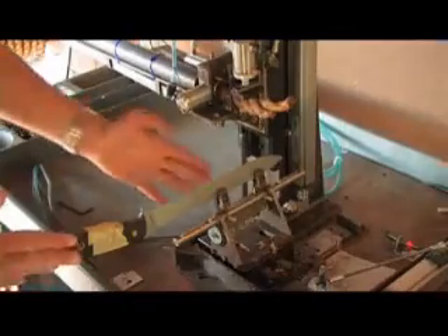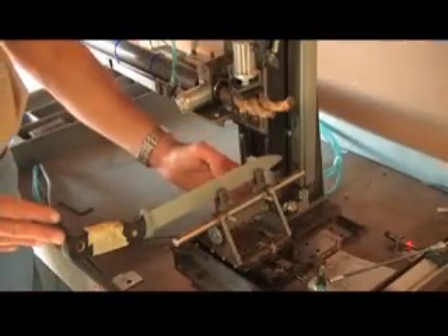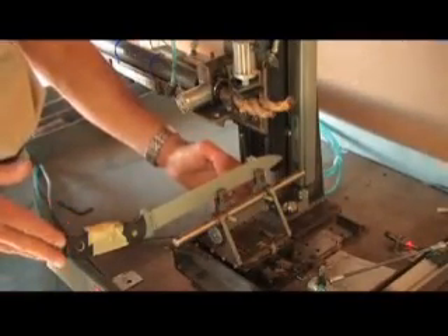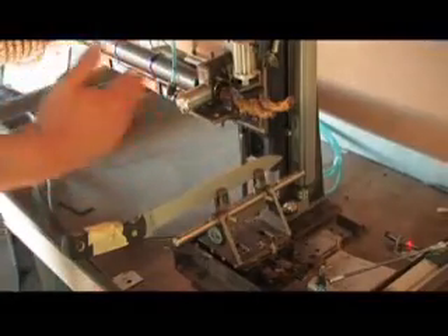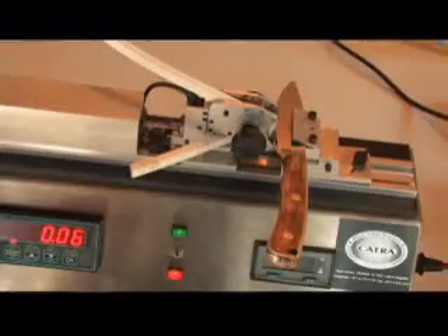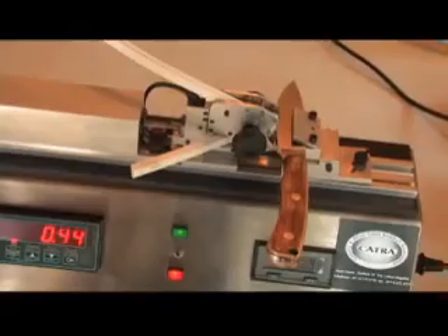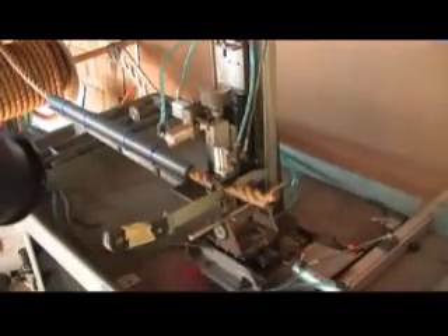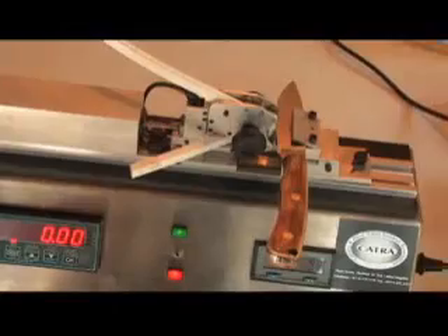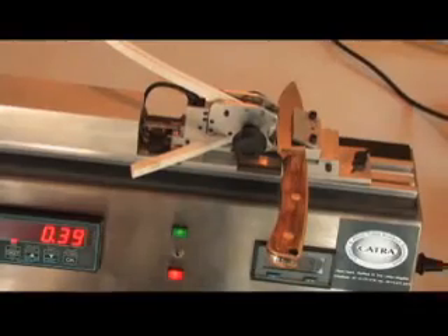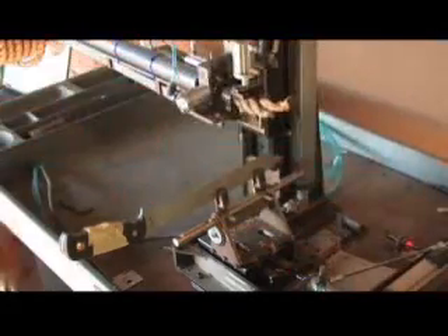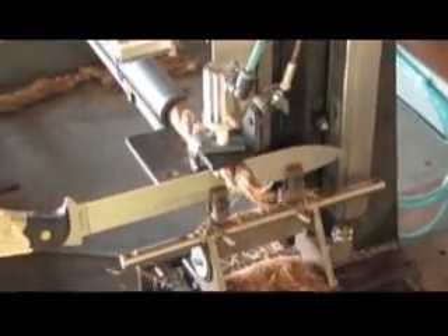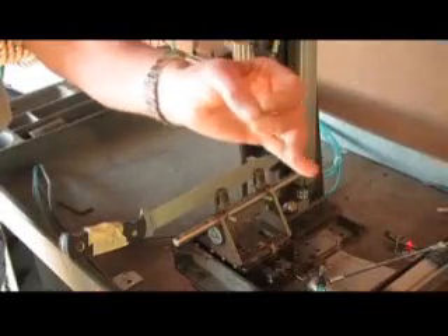So what we would find with materials other than friction forged materials is that with these cuts on the rope, a 3/4 inch standard manila rope, it would dull, as those graphs indicated, much quicker than the friction forged. So the friction forged, we run the test, put it on the rig, conduct a test, back and forth, and we'd find that we were up in the hundreds and hundreds and hundreds of slices before we get to 3.0.